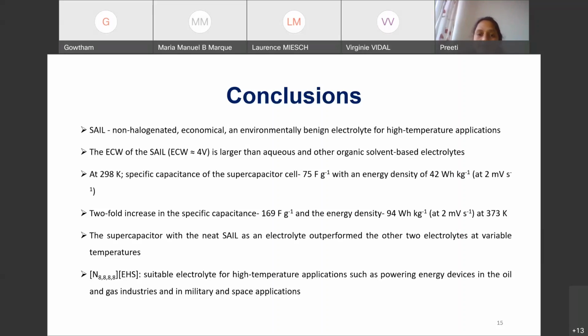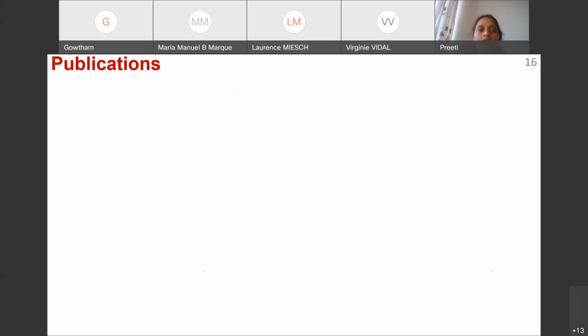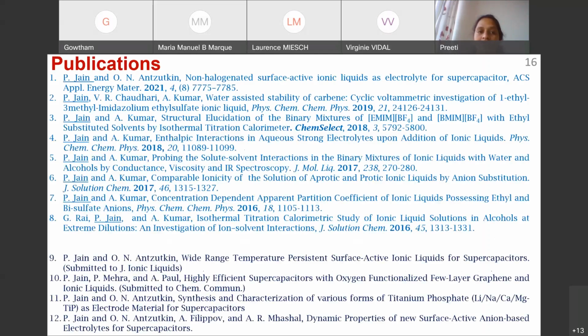As we can see here, the specific capacitance of the supercapacitor is 75 farad per gram at room temperature with an energy density of 42. But we have seen a twofold increase in the specific capacitance and the energy density of the same material, which is very good. And it is suitable for high temperature applications such as powering energy devices, gas industries, and military and space applications. These are the publications.